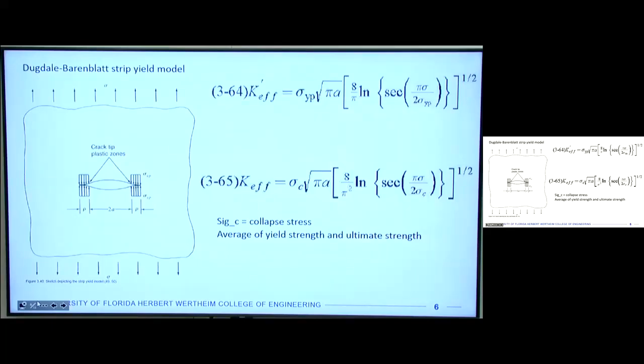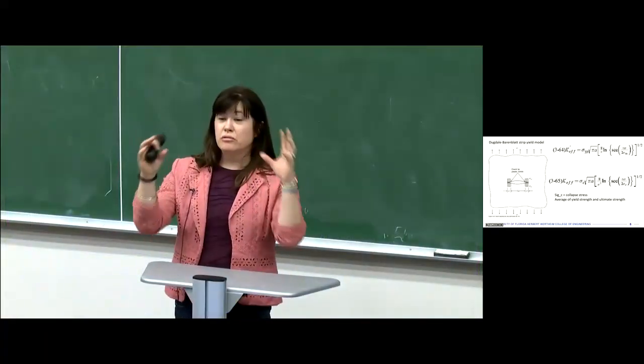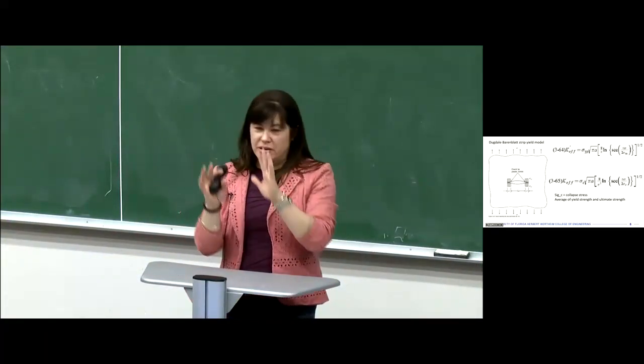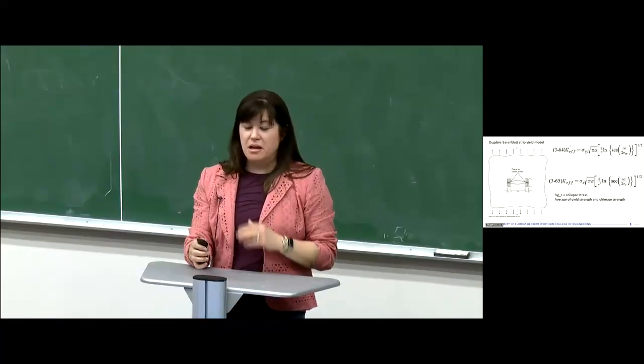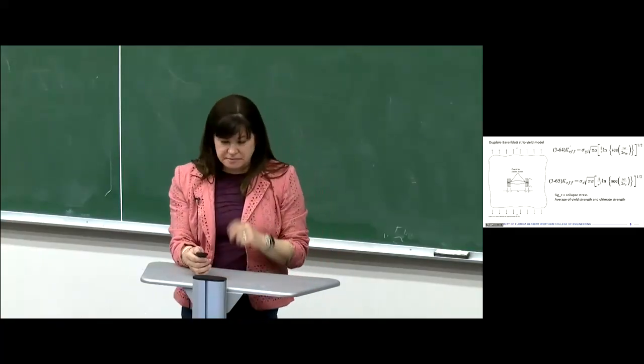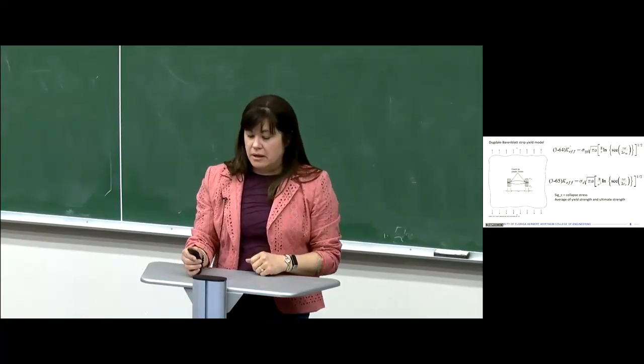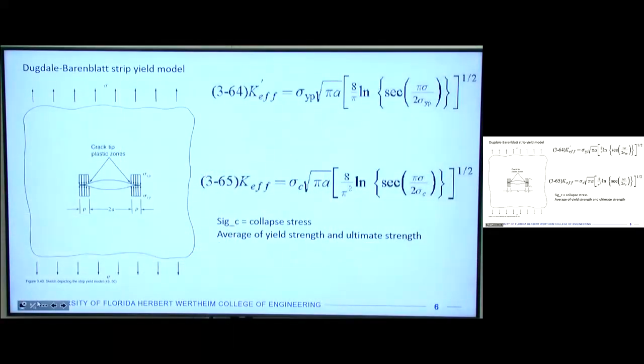And before we said that there might be a plastic region at the ends of that crack, but the plastic region was like a circle that we drew around, and we said, here's kind of where there's probably some plastic deformation based on stress concentrations. And so we can say that because we don't really care what the shape of that little plastic region is. If we're doing linear elastic fracture mechanics, we're far away from the crack tip anyway. But when we have plastic deformation, we can't do that.